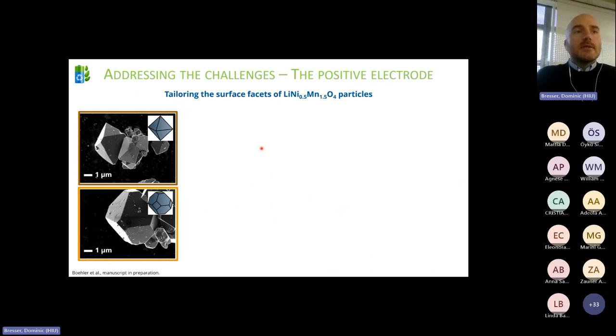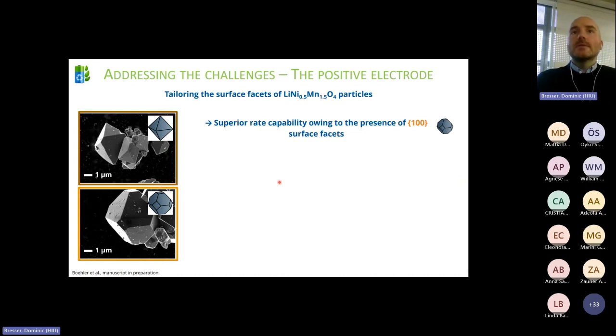Another important aspect that people are working on is particle design, right? Because once again here, the example of lithium nickel manganese oxide, but it's the same basically for other cathode materials. These particles basically have different surface faces with different properties. So this here, for instance, this purely octahedral shape, is covered with only 111 surfaces. And here we kind of truncate, right, part of these edges in such materials.